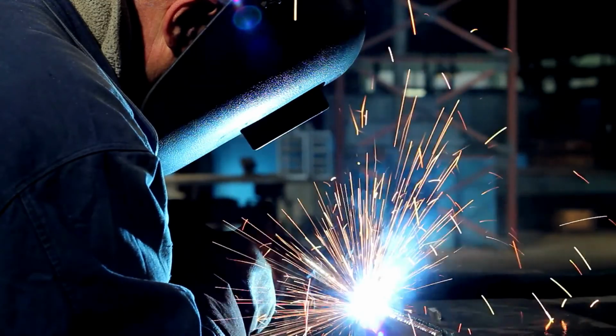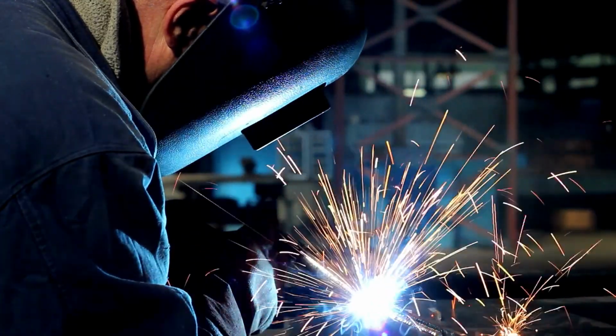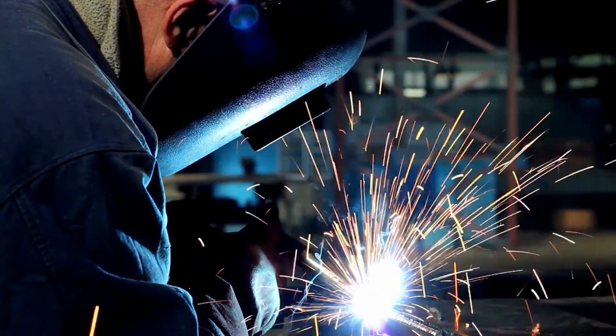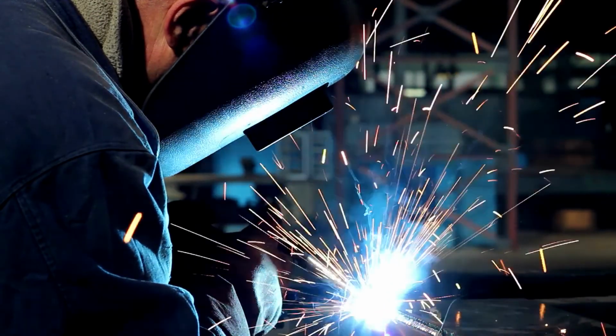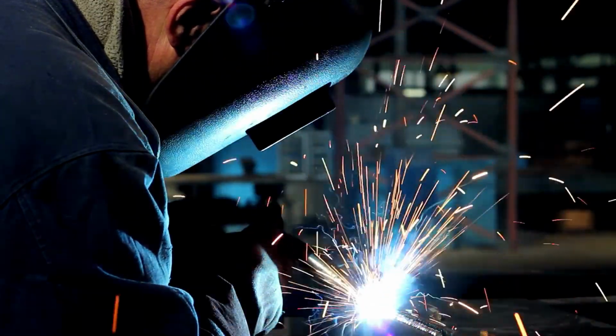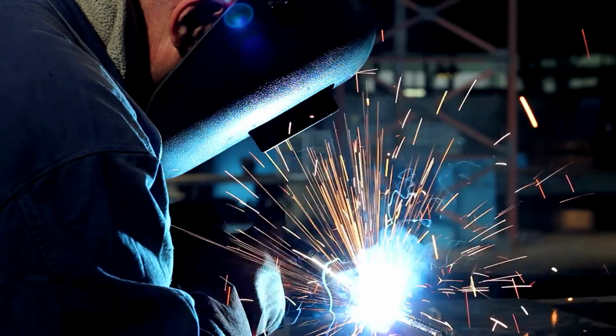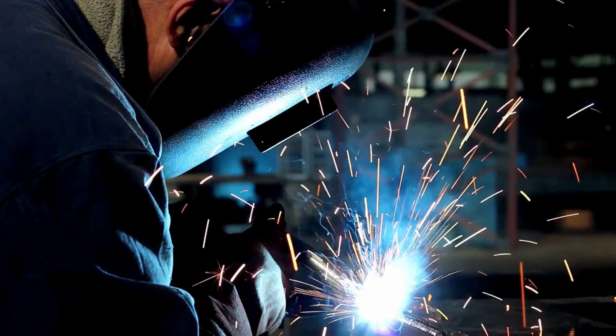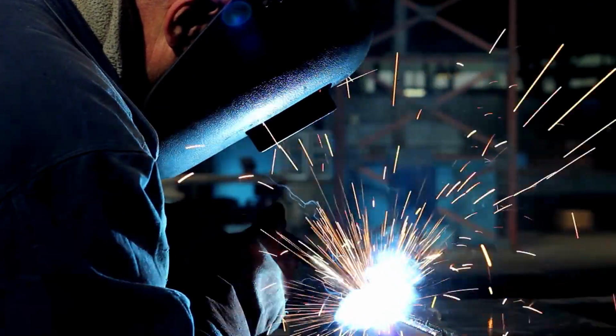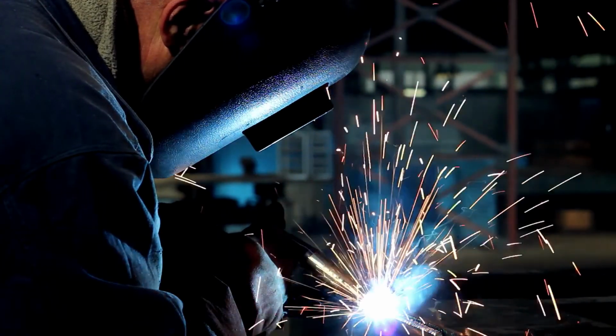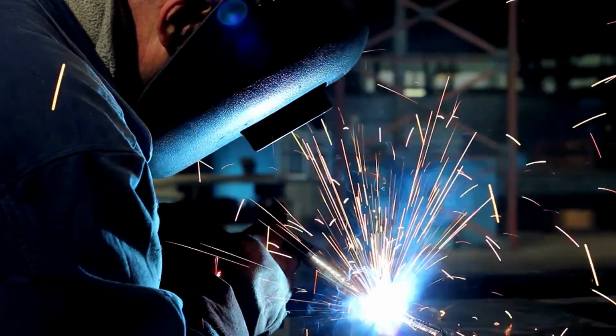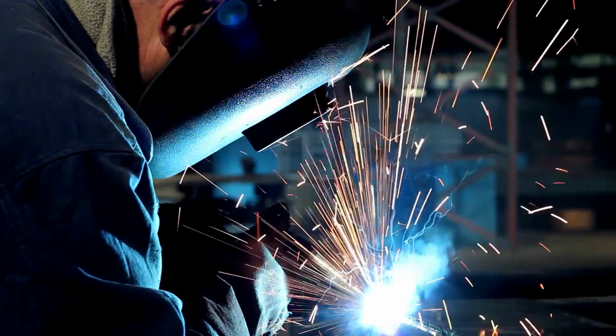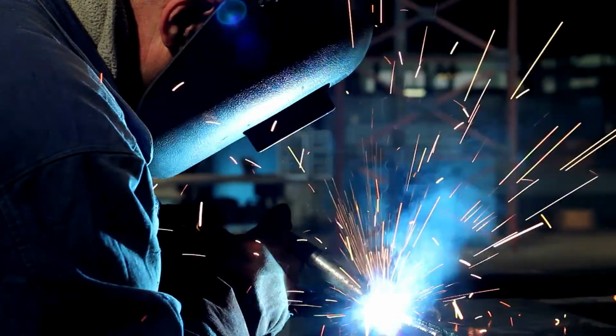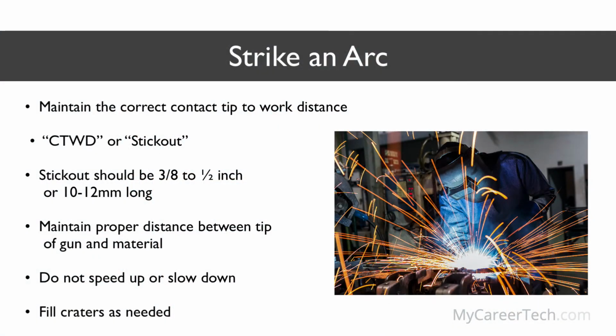If the stickout is too short, the wire electrode can fuse to the contact tip. It also causes the arc voltage to raise, resulting in a flat bead shape, increase in spatter, and possible undercut. If the stickout is too long, the electrode could stub out. It also causes the arc voltage to drop, resulting in a ropey and convex bead, increase in spatter, and possible loss of gas shielding. When laying a bead, make sure to maintain about 3/8 to half an inch distance between the tip of the gun and the material you're welding.